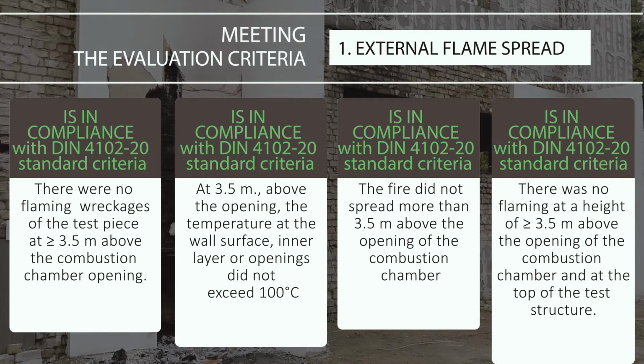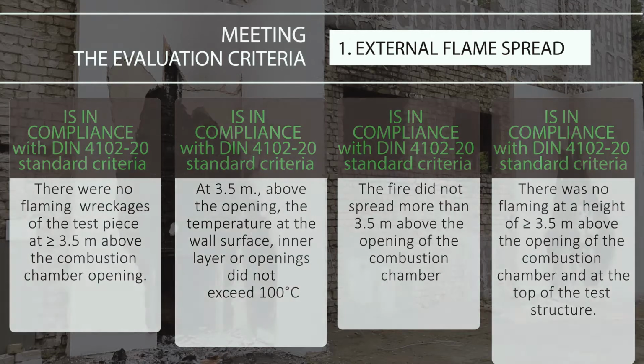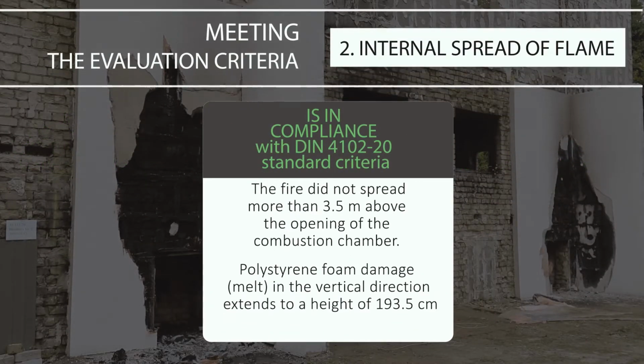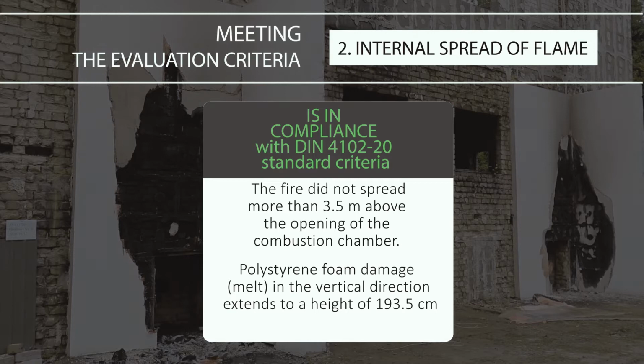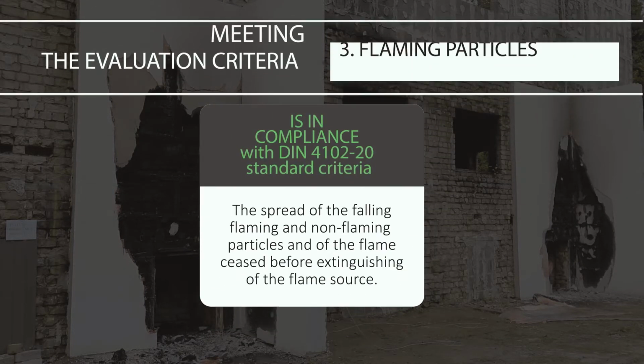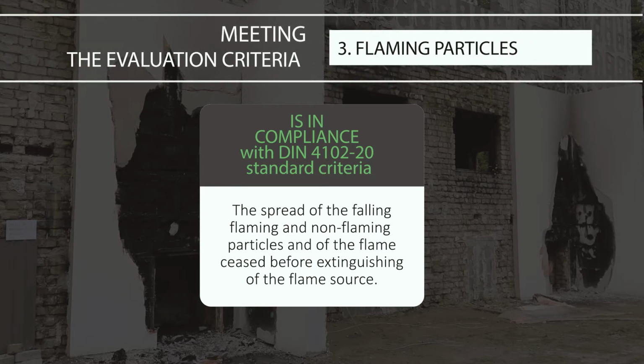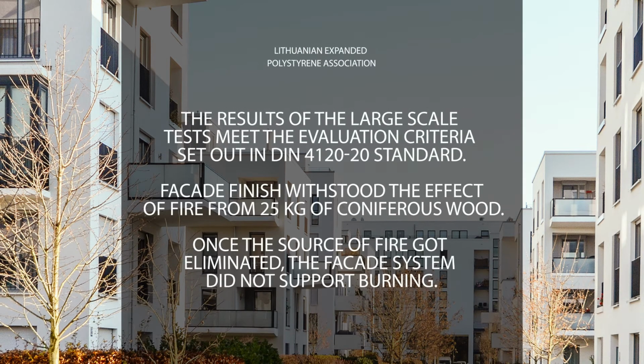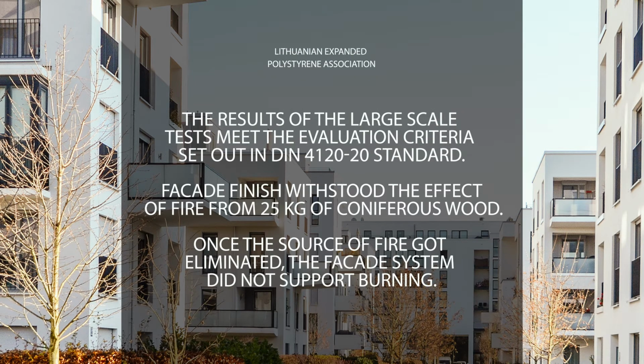The findings of the evaluation of the test pieces with regard to external spread of flame were in compliance with the criteria set out in DIN 4102-20 standard. The findings of the evaluation of the internal spread of flame also met the criteria set out in DIN 4102-20 standard. The findings of the evaluation of flaming particles and droplets also met the criteria. The results of the large-scale tests met the evaluation criteria set out in the German standard method DIN 4102-20. The facade finish withstood the effects of fire produced by 25 kilograms of wood.